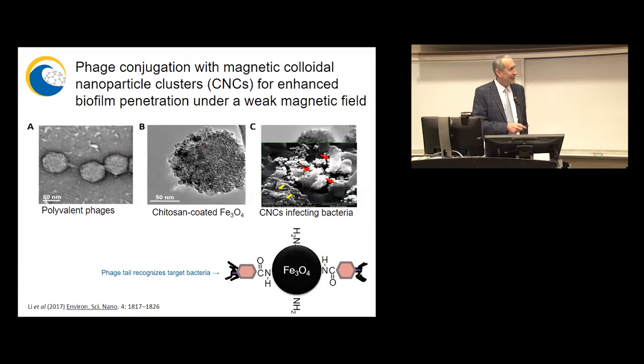So how do we do that? Well, I knew that the heads of these phages have a lot of carboxylic groups. So by coating the nanoparticles with chitosan, a naturally occurring polymer that has a lot of amino groups, we were able to form amide bonds and very easily have them properly oriented. So you get a high concentration of phages oriented in the right direction. You can see them here. These are the little spheres. The large, of course, rods here are the bacteria, and they're killing them right there.